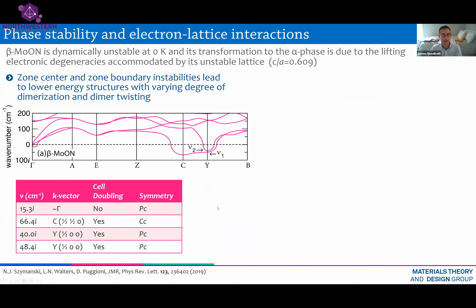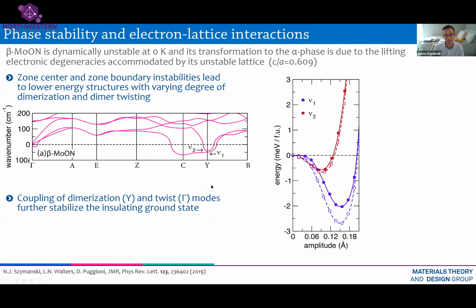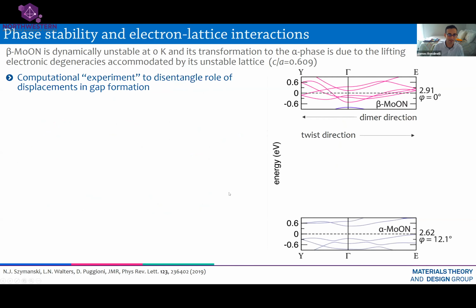Okay. And Nathan went into great detail to understand what is the driving force for this phase transition. And I'm just going to skip through some of these slides here. But what he identified was that the dimerization is derived from what's known as a soft phonon, in analogy to what happens in vanadium dioxide. So this is the first rutile-like heteroanionic material, which really does mimic the physics of vanadium dioxide.